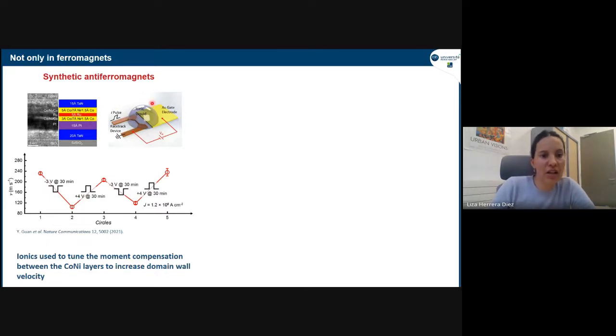So here they used an ionic liquid. They just place it on top of this stack. And what they did is to actually oxidize the top layer. So then that would bring it closer or further away from compensation with the bottom layer. And then when they get close to compensation, domain wall velocity shoots up. And that's really what they show here.